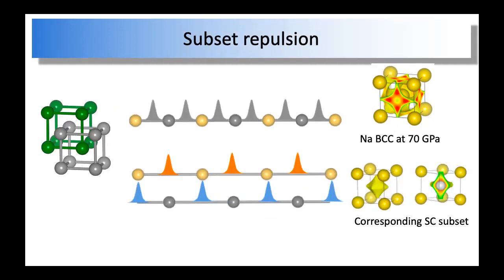On the other hand, if you compress the sodium BCC up to 70 GPa and calculate the ELF for BCC, it doesn't change much, right? The localization maxima are still at the tetrahedral site. However, if you calculate the electron localization of the subset of the simple cubic, now it's totally different. The electron localization moves. Remember, as you shrink the lattice, it tends to move to the site that has more neighboring atoms. So if you compress it to 70 GPa, then it moves to the body center site. Okay, and the body center site is exactly the location of the atoms of the other subset.